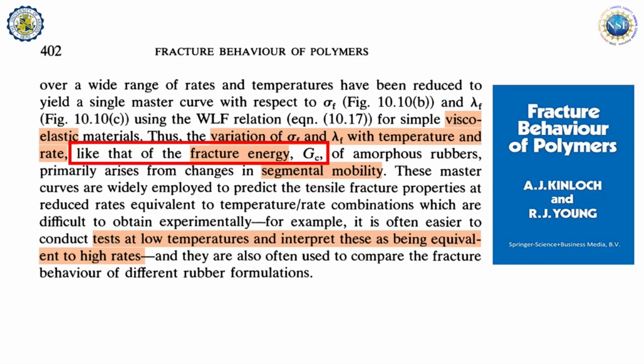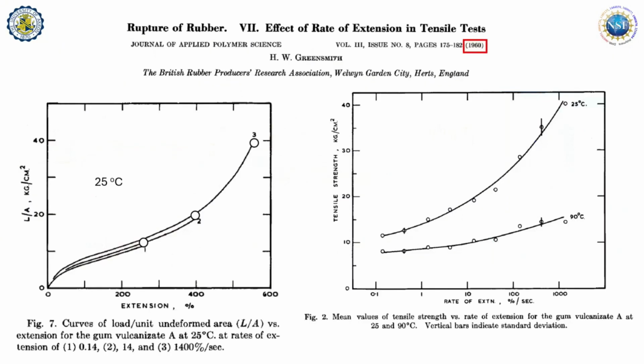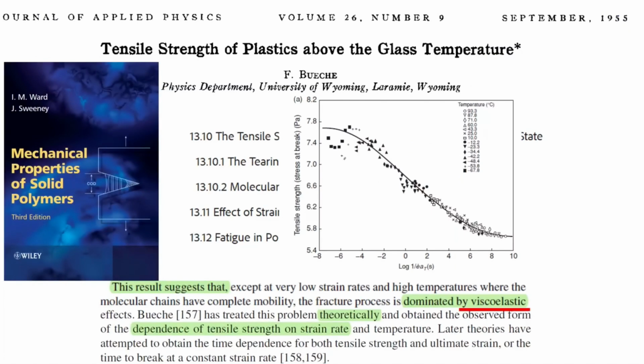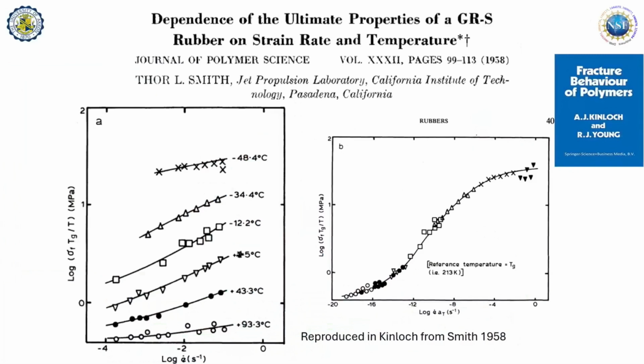In other words, when I stretch slowly, I can only stretch this much. When I stretch fast, I can stretch more. When I go to lower temperature, I can stretch more, which is equivalent to stretching at a higher rate, according to our dear WLF. Every polymer person here knows this must be right. So here's the data, right? Again, nearly 70 years old. Stretching at 3 different rates. You just stretch more before it fractures, it ruptures. We use the word rupture to indicate there is no notch. And better yet, at the lower temperature, it's stronger. Wow, you can now see the deal. Do a horizontal shift. And so, indeed, they do the horizontal shift. You get a master curve. It's all summarized in the textbook, and it's all about viscoelasticity. Largely. One more. This is a more systematic piece of data done in 58.